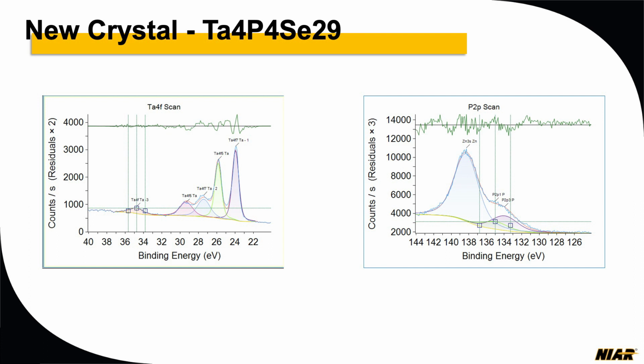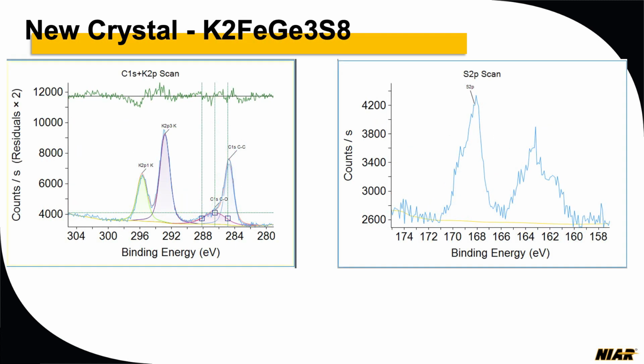I don't believe I've shown that one. Okay, that's not in here right now. But that is for one of the crystals, and one of the professors is trying to publish work on this, so we're not sharing a lot of information, just limited to this at this point. Another crystal that we created, as he mentioned, is a potassium, germanium and sulfur combination, used as a thin coating on top of a glass material that can reduce laser energy levels. In there we identified the potassium states, different carbon states and sulfur.